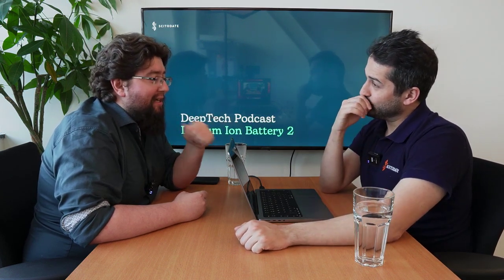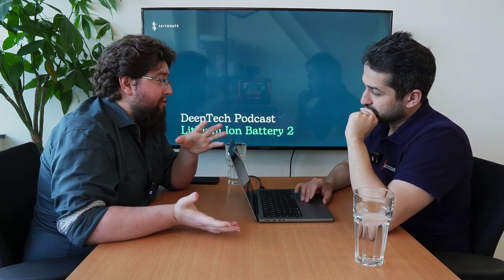It has a harder time going inside, so it stuck to the surface, and then slowly it lets less and less lithium in, because it essentially coats the surface. So even if you charge it again at a high temperature, you still have the plating. And there are two sides. One blocks the other lithium ions. The other one removes lithium ions from the whole system. So there are fewer marbles, because it's not a reversible process anymore, so they get stuck in there. The marbles you had to play with, you have less and less of, because they are stuck on the surface. So there are fewer marbles in the game.